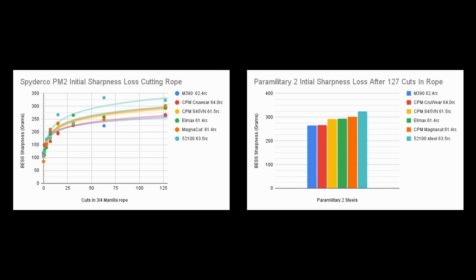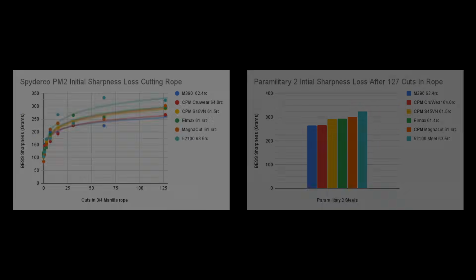This is why sometimes I prefer to test different properties separately, such as CATRA for edge wear, hardness for strength, toughness for chipping resistance, etc., so that we can choose steels based on their strengths and weaknesses. When we do a test like rope cutting, there are a combination of factors at play, and the edge geometry we choose will also change the balance of which properties are important. This can make it difficult to figure out exactly what is going on. That doesn't make rope cutting tests bad, it just makes our analysis more challenging. I like the set of tests that Sean did because it illustrates well how hardness and wear resistance can add up together in a specific scenario.